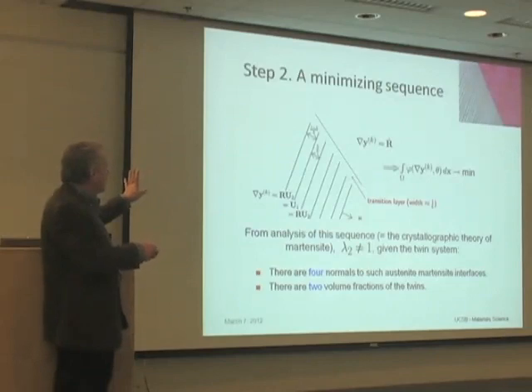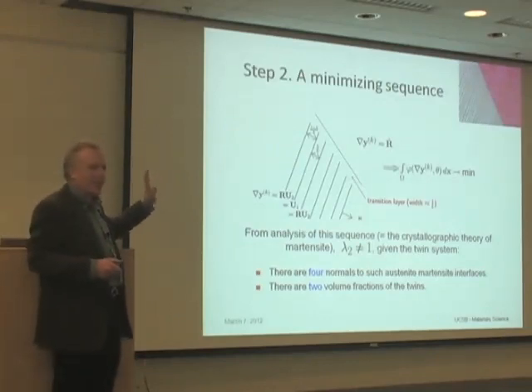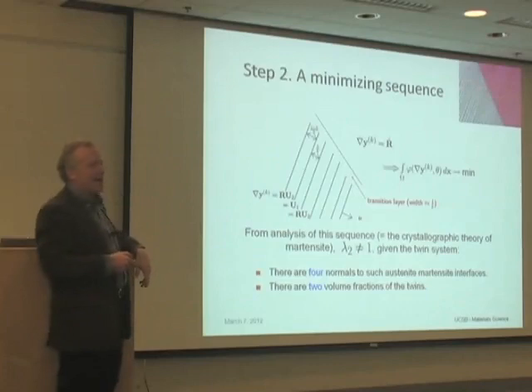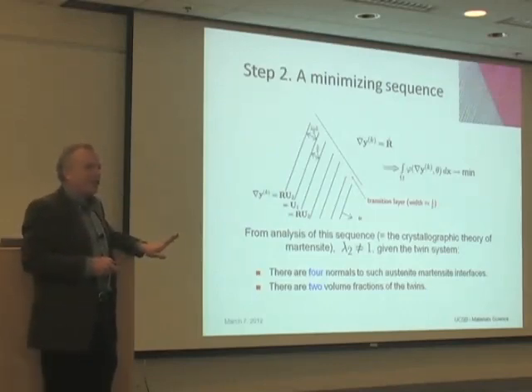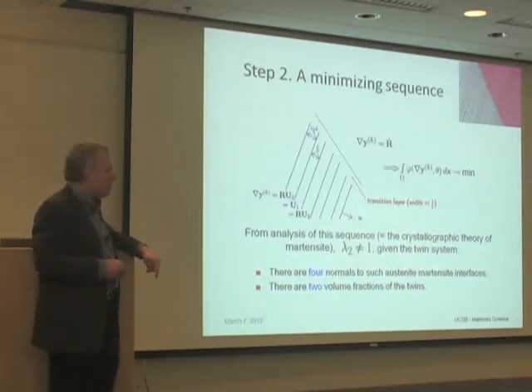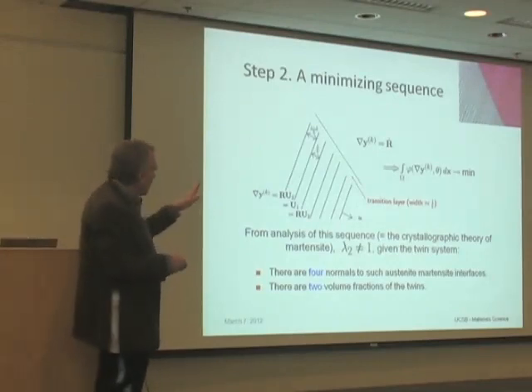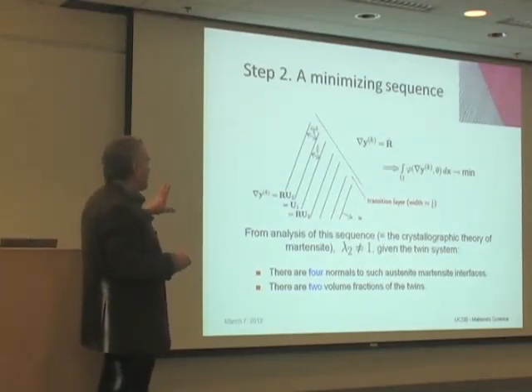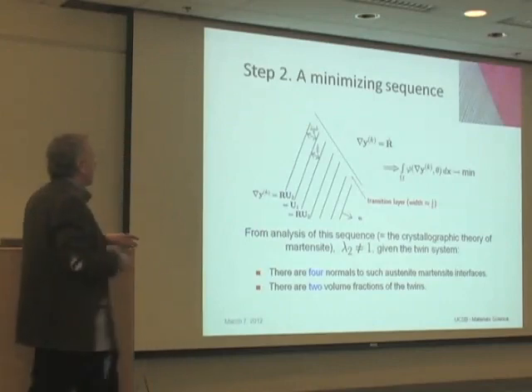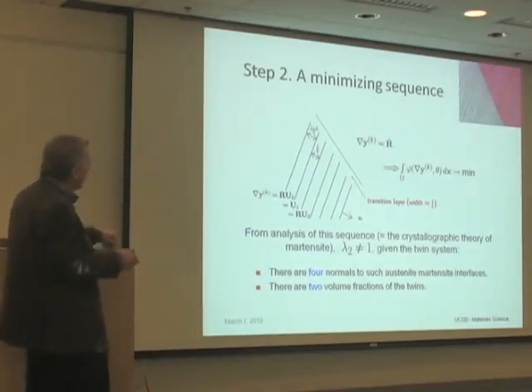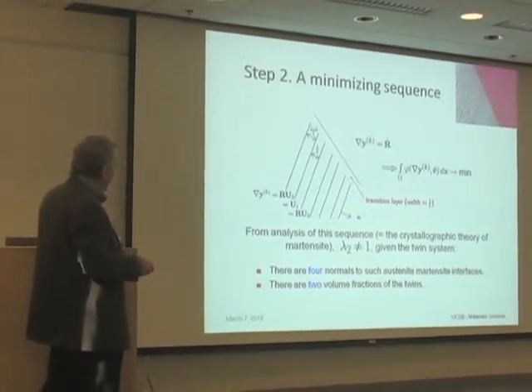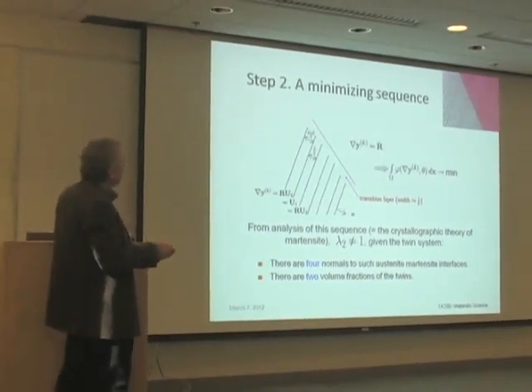And so this picture represents a compromise between the interfacial energy on the twins and the bulk energy in the elastic transition layer. Okay? That's well accepted, and there are many points of contact with experiment that I'm not telling you about, about the fineness. I already talked about the geometry, but to predict the fineness correctly, you need to bring in this interfacial energy, and there's also branching here that's also understood. So there's a lot understood about this picture.